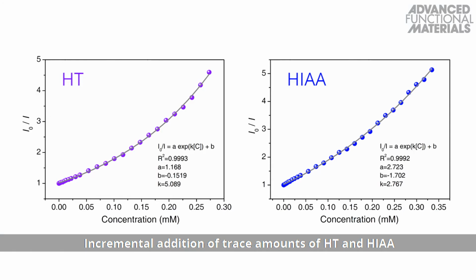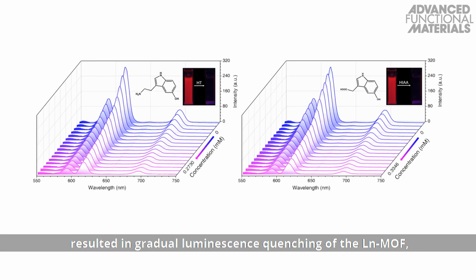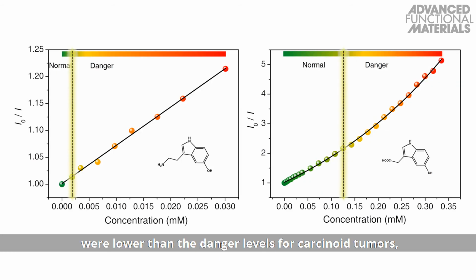Incremental addition of trace amounts of 5-HT and 5-HIAA to an aqueous suspension of the lanthanide metal organic framework resulted in gradual luminescence quenching of the lanthanide metal organic framework, as seen by a colour change from red to colourless under 254 nanometer illumination. The limits of detection were lower than the danger levels for carcinoid tumours, making this lanthanide metal organic framework suitable for early diagnosis of the cancer.